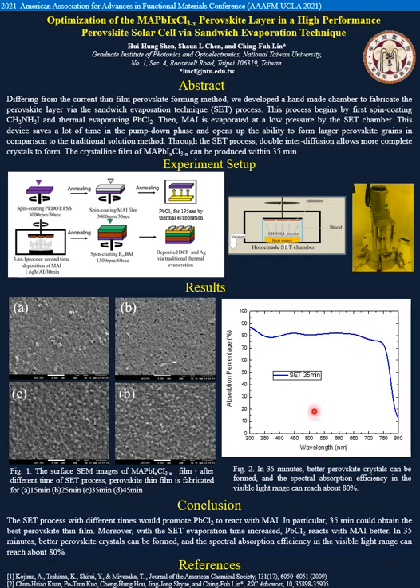In Figure 2, we can see that at 35 minutes, the perovskite spectral absorption efficiency in the visible light range can reach about 80%.